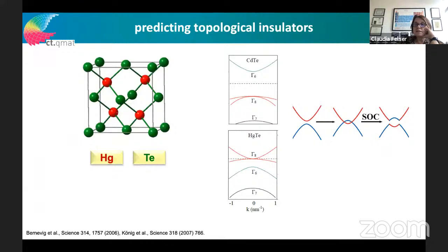So I always have to make the bridge to my most favorite class of materials. As I said, in cadmium telluride the s band is above the Fermi energy, and it's nicely seen that in mercury telluride this s band—the gamma 6 band—comes below the Fermi energy. So you have this very nice band inversion here.